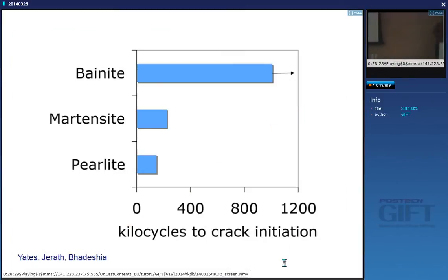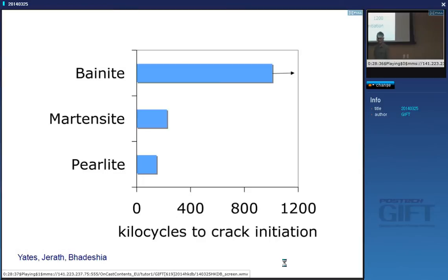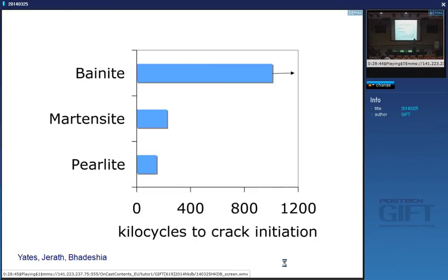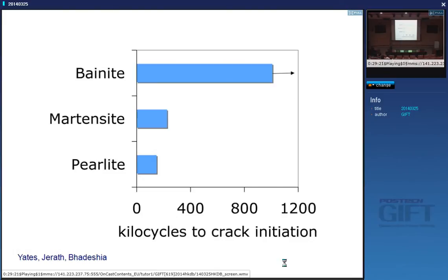In the bainite-austenite structure we designed there are no carbides at all — it can be tough, and we've seen that it is tough. So we made railway lines out of this structure. One of the damage mechanisms very common in railway lines is rolling contact fatigue — a wheel goes over a rail causing a large stress pulse under the surface each time, and after a while the crack under the surface spreads and a bit of the rail comes off. These are full-scale tests on the new structure. For the normal pearlite rail, hardened pearlite rail, and the new carbide-free bainitic rail — there was no failure for the new structure.